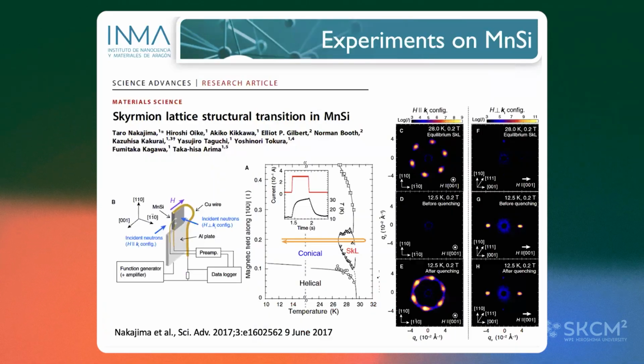But before, we were very happy because here in Japan, Nakajima sensei published at the same time as our paper, in 2017. They did a very nice experiment in manganese silicide. They take a crystal and put two wires on it in order to pass a current through the crystal. I will explain this experiment because it's a very nice experiment. This is the phase diagram of manganese silicide with the so-called A phase. They stop at 28 Kelvin, 0.2 Tesla, that means this point.